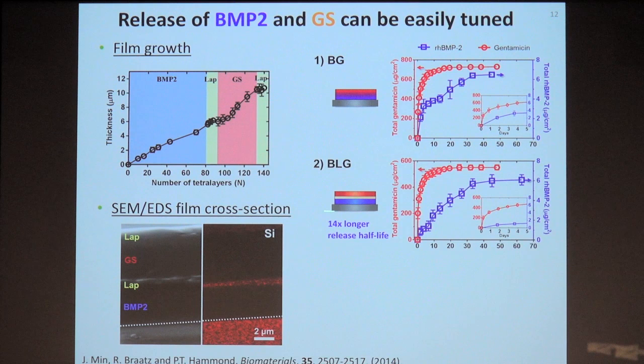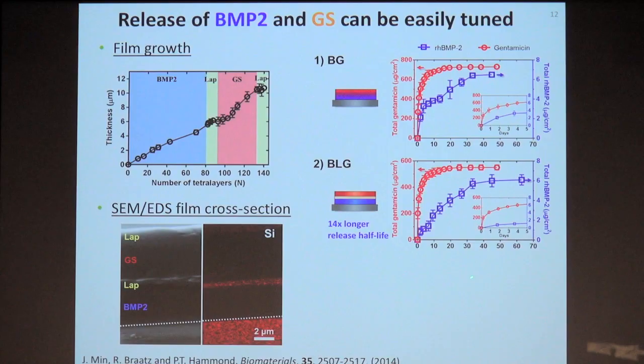If she puts just a singular set of laponite layers in here, then she gets a 14 times longer release period for her BMP2. So here you can see that it's sort of drawn out over time, whereas the gentamicin is unchanged. So that diffusion layer is helping to slow down the rate at which BMP2 arrives. And that helps in clearing the infection early and then generating new bone.